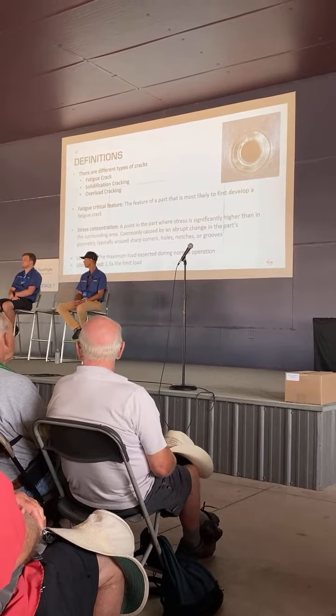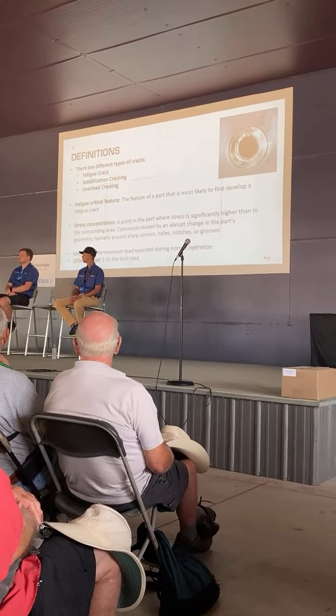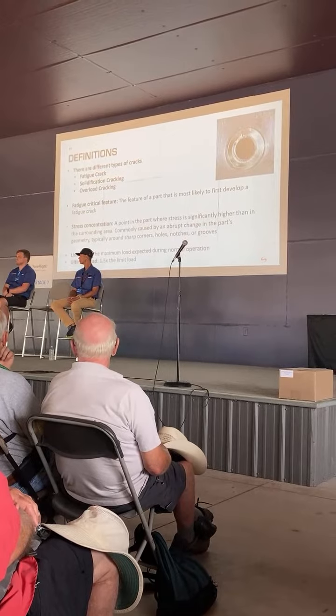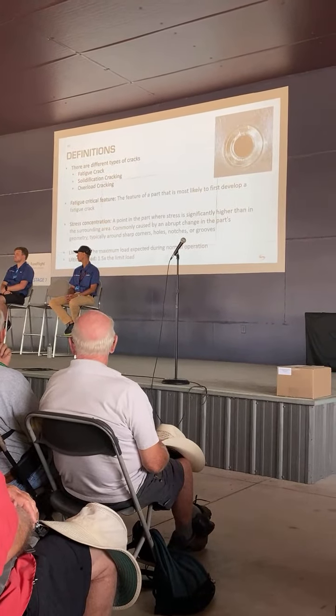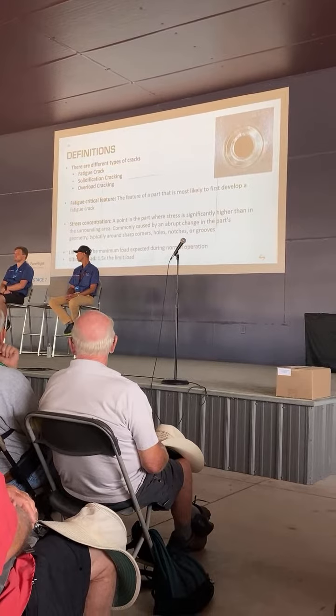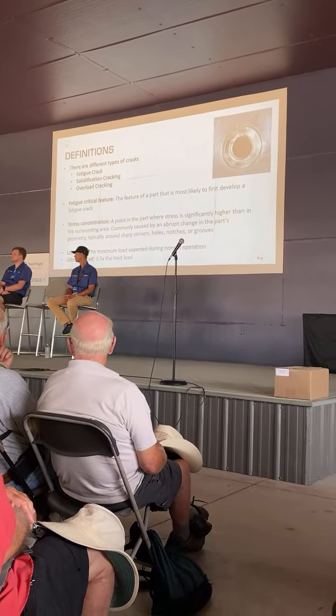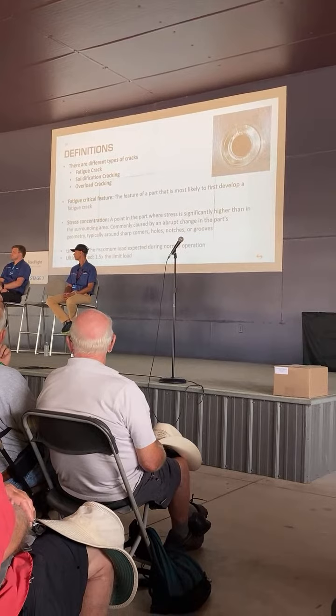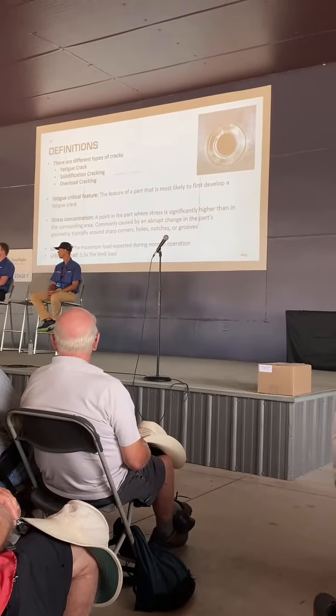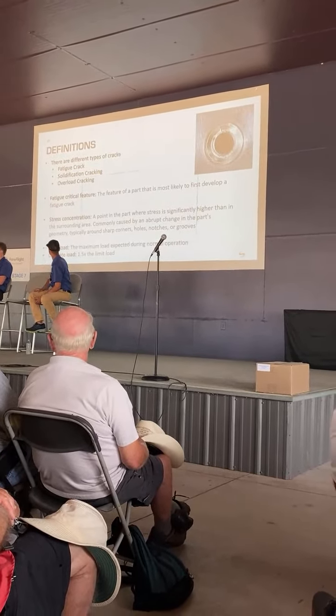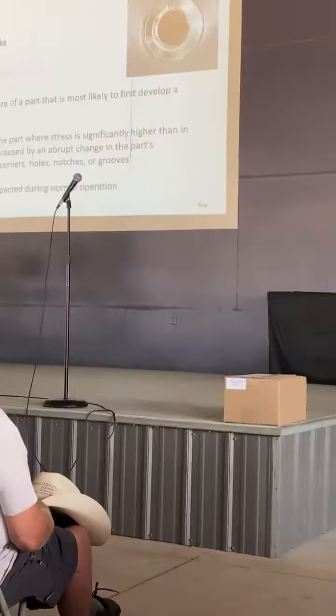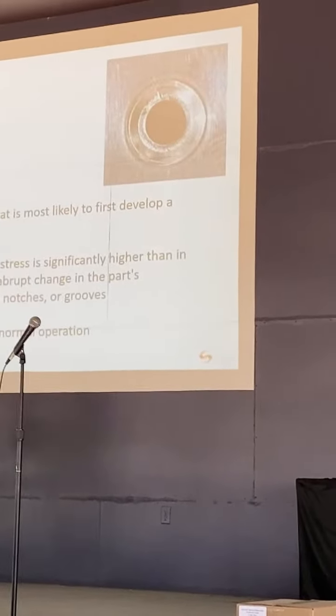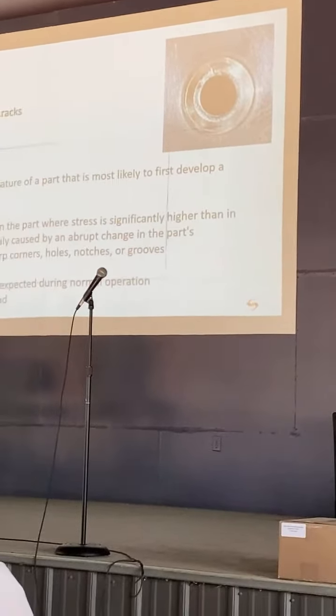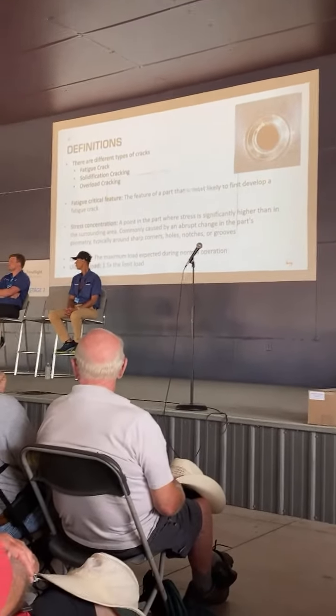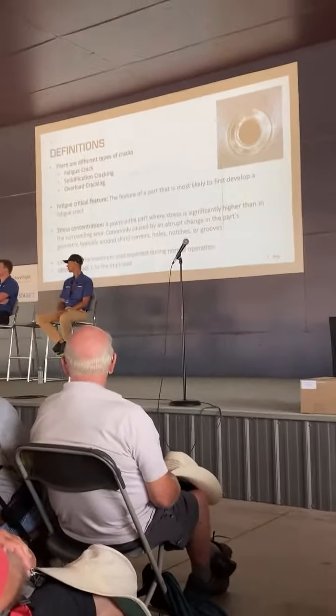Overload cracking, that's a term that I'm just going to coin for this presentation so that we differentiate between a fatigue crack and an overload crack. An overload crack, what we're defining that is a crack that's happening during the dimpling process. So you can see in that upper picture, laser pointer here, there's a crack that's opened up right there during the dimpling process. So that was what has been more recently reported at VANS and caused us to go back and take a look at what was going on in the process.